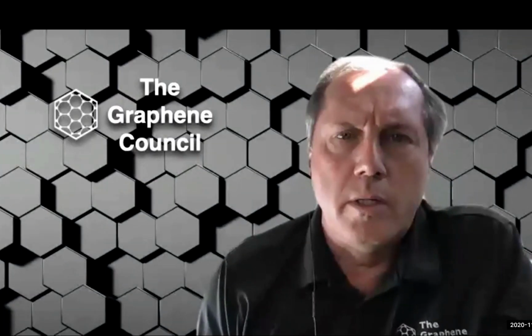So around the tooling and processability, from our experience in the GEIC using graphene-enhanced prepregs, handling prepregs, we've not seen any difference whatsoever. We haven't had to alter any cure cycles from regular prepregs. So if someone's got a resin system and they just add graphene to it, we generally stick to the same cure cycles and post cures, everything. So we don't actually have to change much at all.